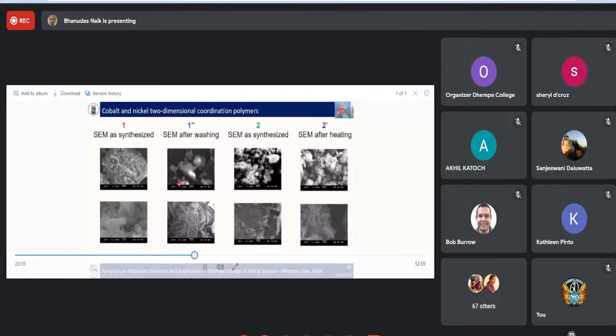You can see in the scanning electron microscope images that the compounds are like a block here, and you can have some lamellar forming here. But when you wash them, they seem to break apart, and you now have very thin plates. You can see very thin plates have formed here. In the same case as 2, if you have 2, it's a blocky crystal compound, and after you're heating up, you seem to have also the very thin sheets which are formed.